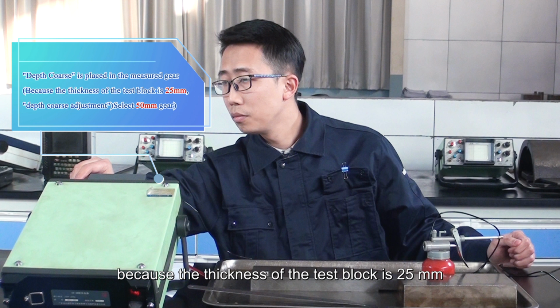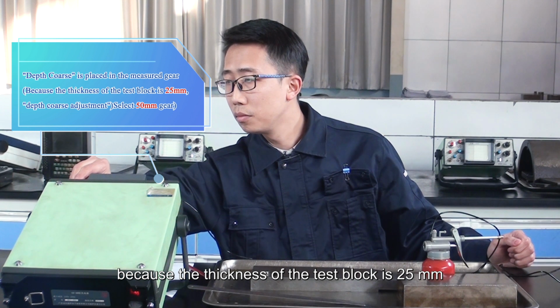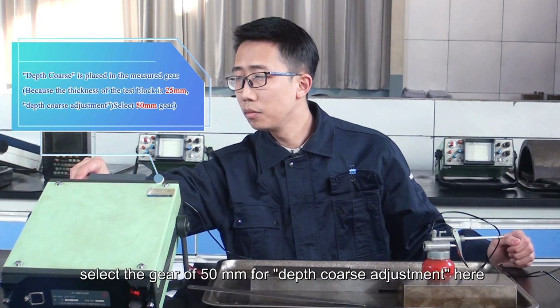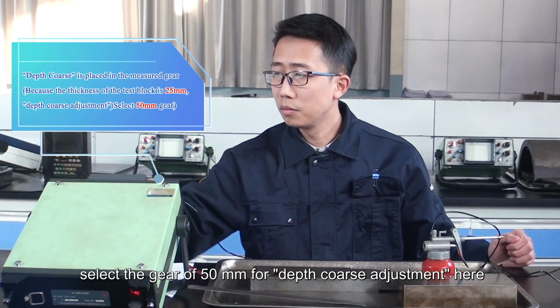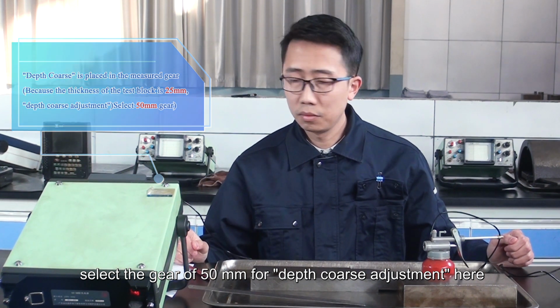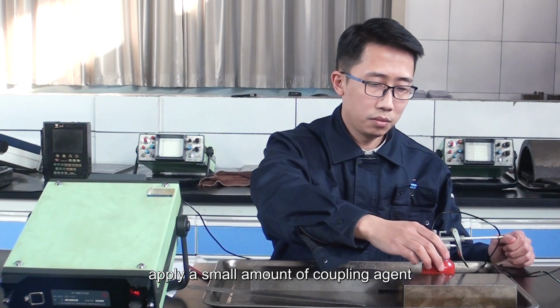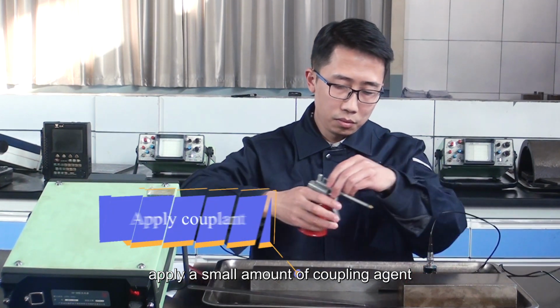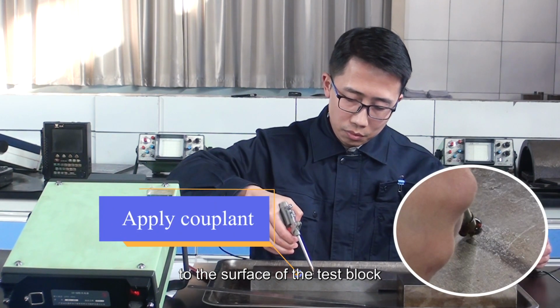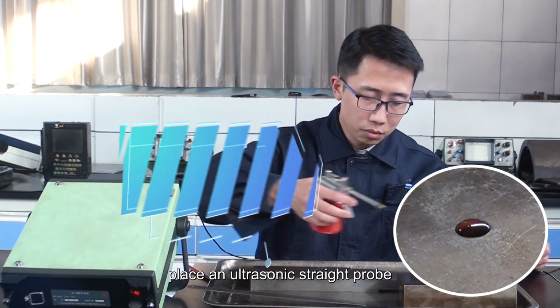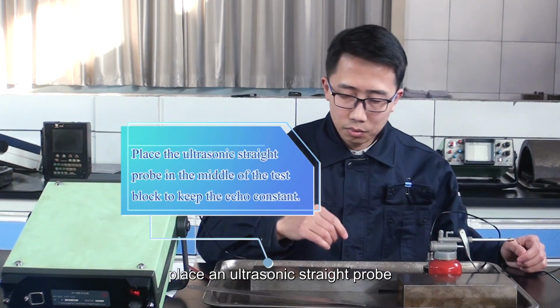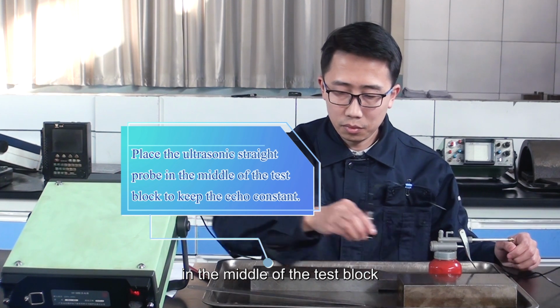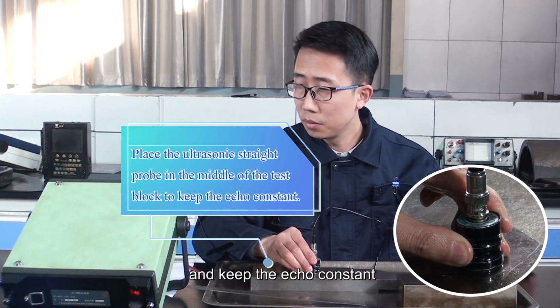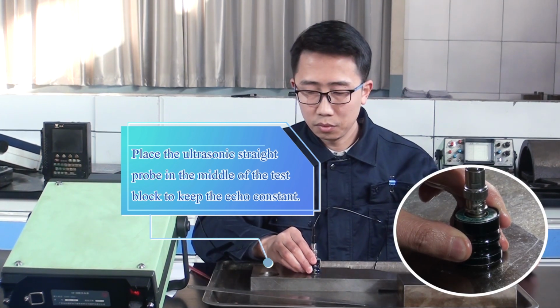Because the thickness of the test block is 25 mm, select the 50 mm gear for depth coarse adjustment here. Apply a small amount of coupling agent to the surface of the test block. Place an ultrasonic straight probe in the middle of the test block and keep the echo stable.